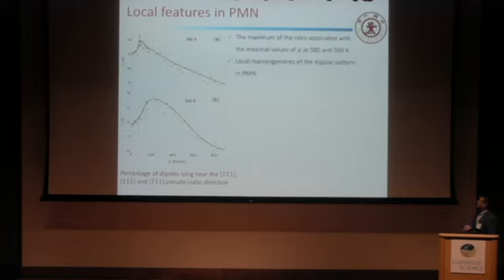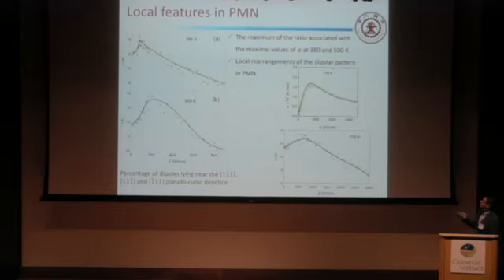We also check at a higher temperature. You can see this is the EC coefficient as a function of electric field. We find a peak around 1,000 kV per cm. We also found this peak is associated with the local feature, the percentage of dipoles.